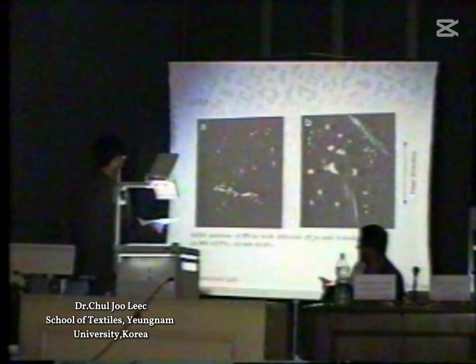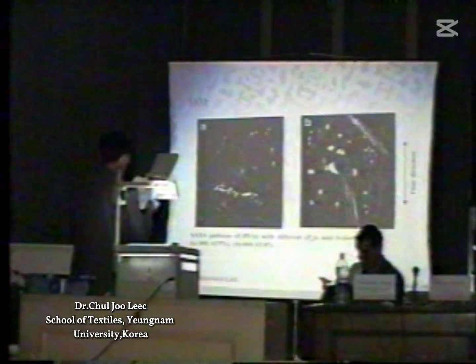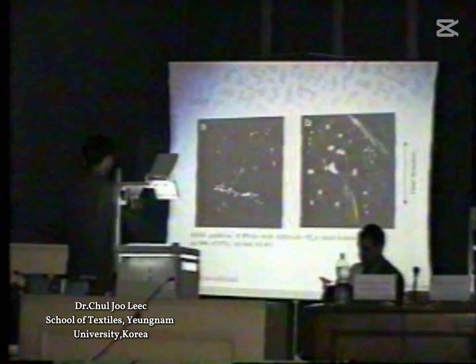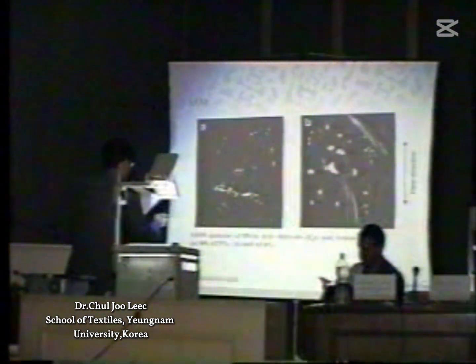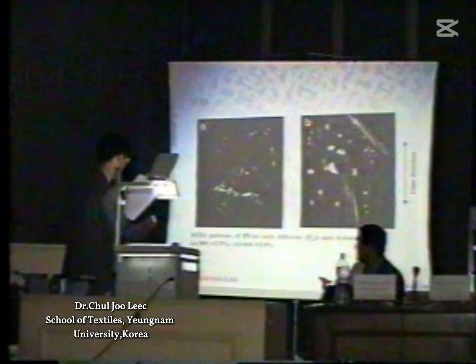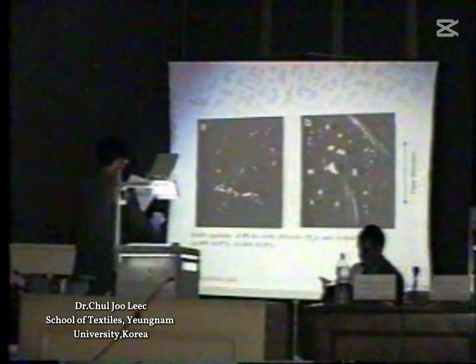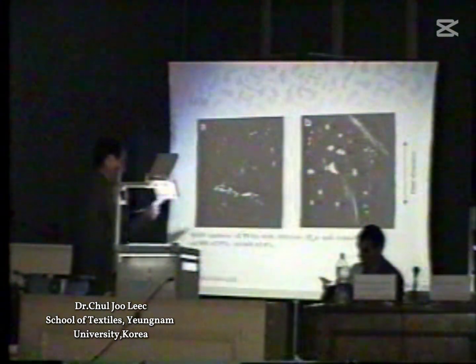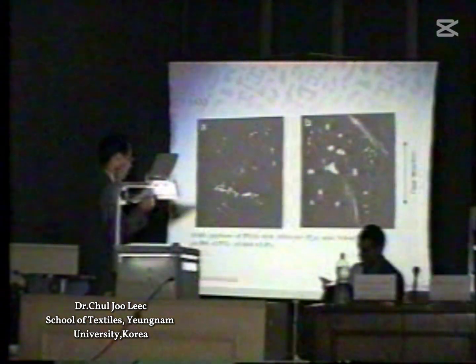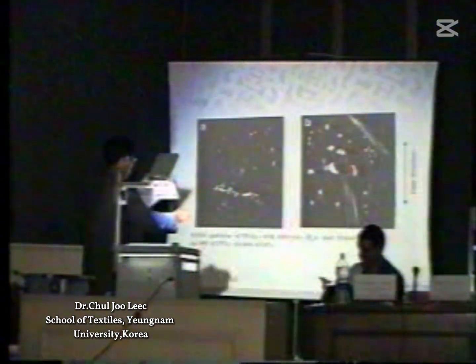These are the small angle X-ray patterns of the same PVA samples. Figure A is the high molecular weight polyvinyl alcohol. We can see the diamond-shaped pattern, but it is not clear. So you may not see the pattern, but the diamond pattern is still there. The diamond pattern is the unique characteristic of microfibrillar structure. It means the microvoid is in the fibrils. However, the low molecular weight polyvinyl alcohol doesn't have that unique diamond-shaped pattern.